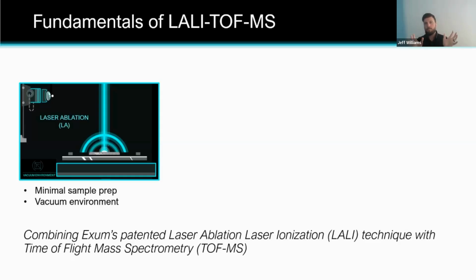And this all happens inside a vacuum, right? So this is great for obviously everybody on the call in the anode space or cathode, where you want to have air-free transfer. You don't want to expose this to oxygen. And we have the ability, and we'll talk about this later, to take it from a glove box, put it into our system, fully air-free, and it goes into a high vacuum environment so you can analyze it natively. And very minimal sample prep. We just need solid and flat, and we'll go into more details.